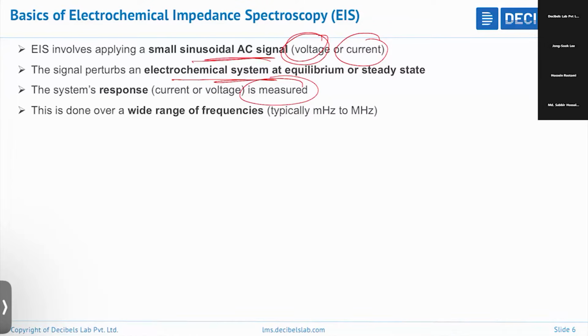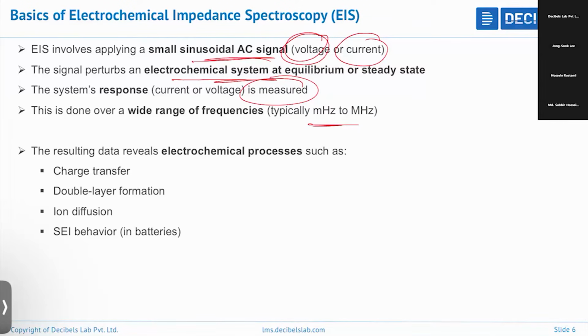And this is done over a wide range of frequencies, typically from millihertz to megahertz, because when you look at the movement of the lithium ion inside the battery, sometimes it is fast and sometimes it is slow. Therefore, we have to perturb the system at various frequencies in order to extract the information of all the lithium ion behavior in all the stages when it is moving.